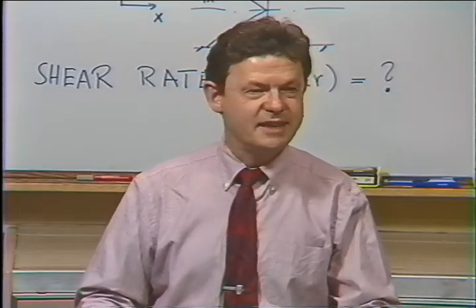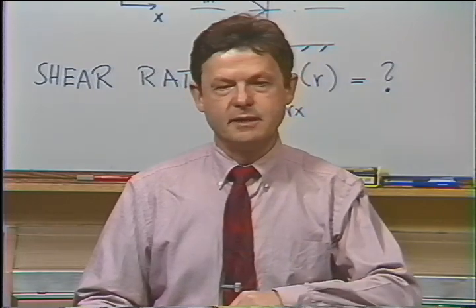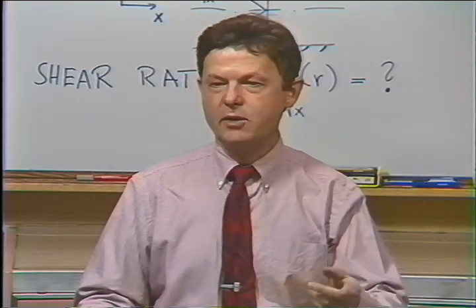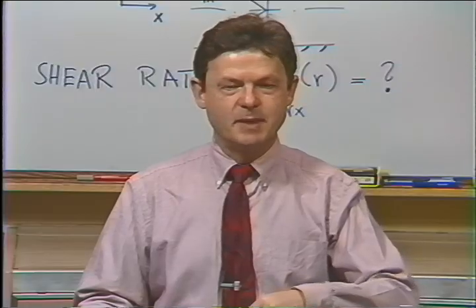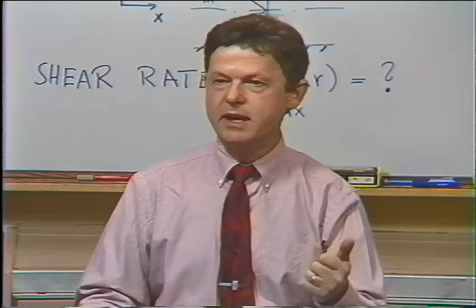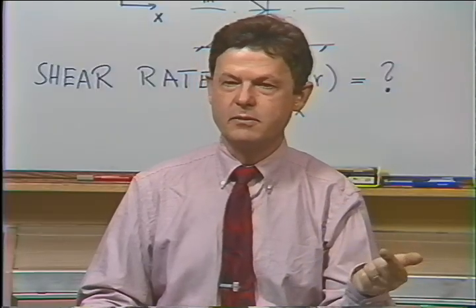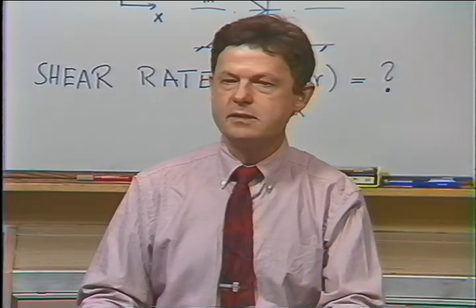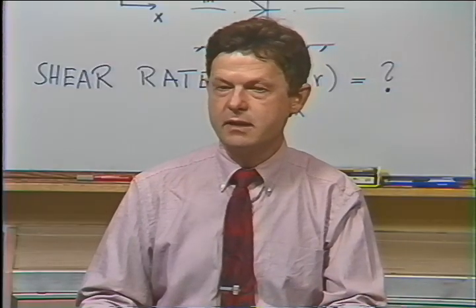You don't need the gradient dq, d tau. You don't need the experiments over a whole range. You take a point value for the shear stress and for the volume flow rate. You use this analysis, you immediately get your viscosity. So it's very, very simple.